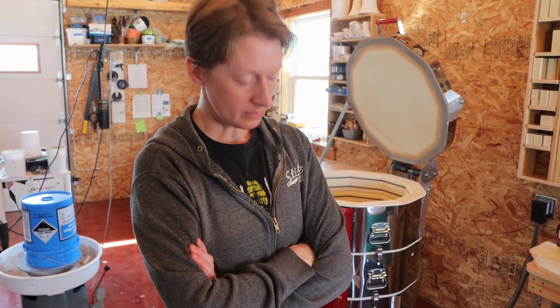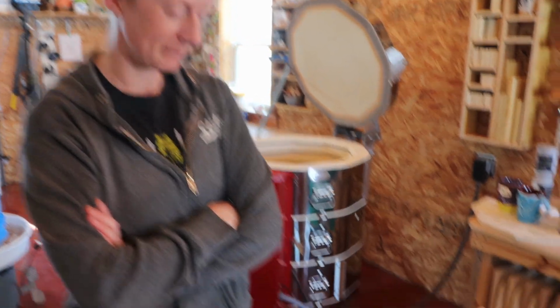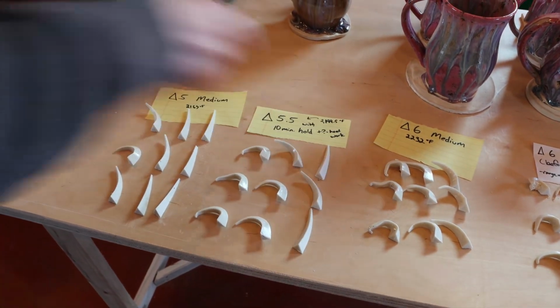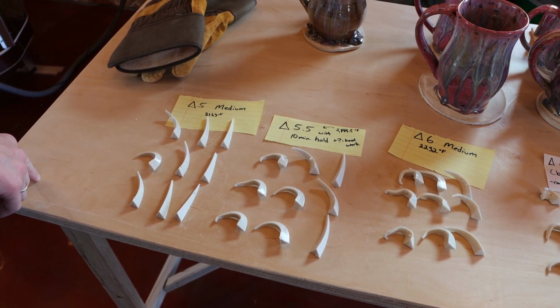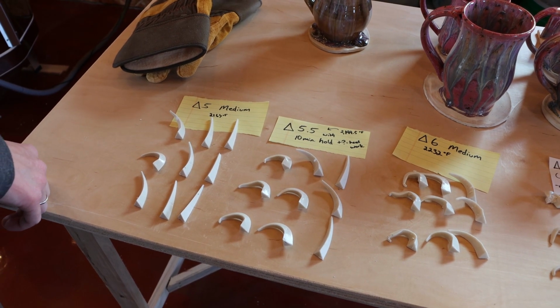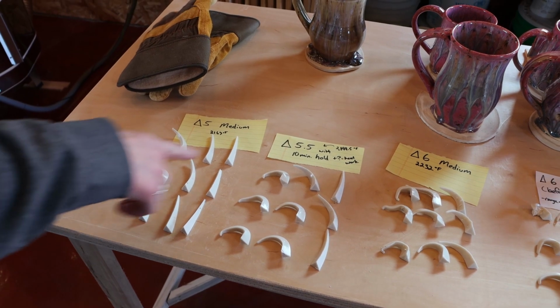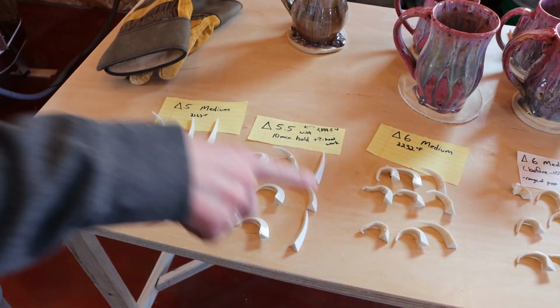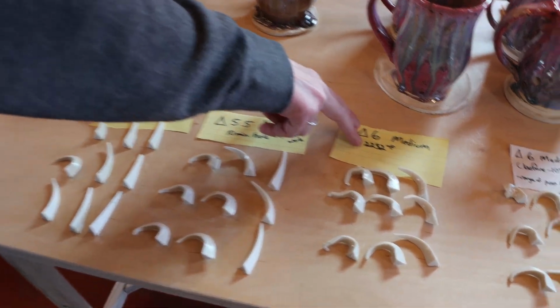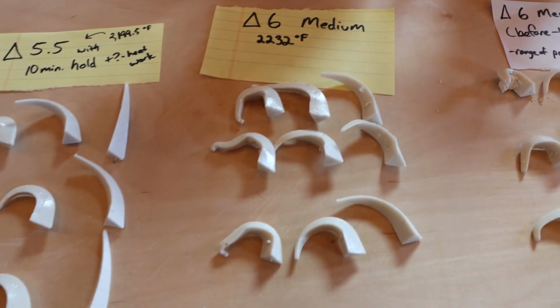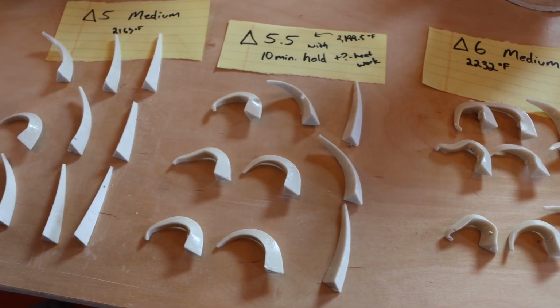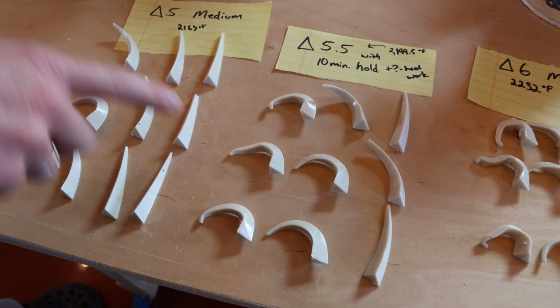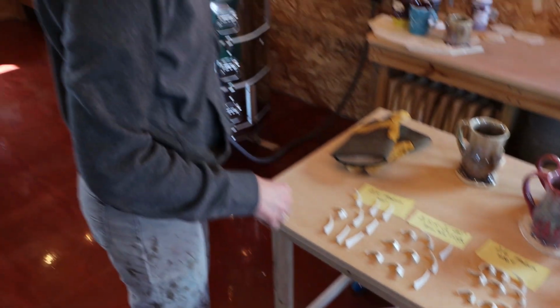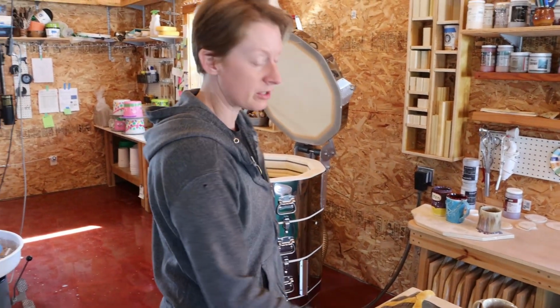So in conclusion, we did 6 separate firings to try and figure out heat and how to control heat on the kiln. Here are our results. The first 3 were still all firings with glaze pieces in it, and I just wanted to see if I could tweak something with the limited knowledge that I had to make a cone 6 not fire so hot, because it's definitely going above the 2232 it's projected to be. So then I tried the cone 5, and then I went back to the middle and tried a cone 5.5, which is about a 30 some degree difference, just to see if I could control the temperature, which I found out I could.